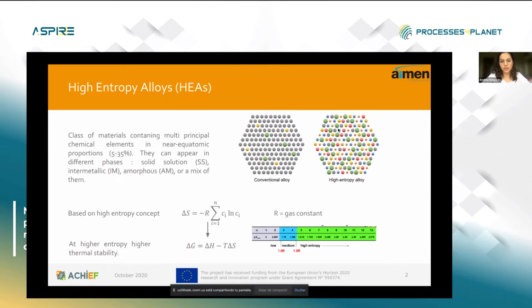Due to the presence of these multiple principal chemical elements in the high entropy alloys, this gives rise to a high entropy, which is computed with this formula. This is important for the concept of Gibbs energy, which is related to the stability of a system. So the higher the entropy, the more stable the system will be. So that's really important for the stability. This entropy is really important for the stability of the final alloy and also for its configuration. Just to make it a little bit clearer, in this graph we can see that for values bigger than this one, we can consider an alloy to be a high entropy one.